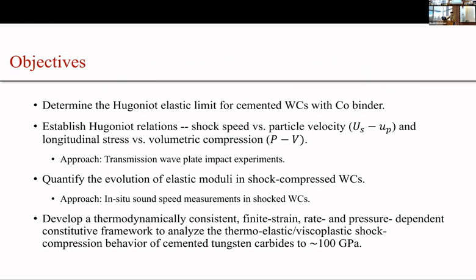The overall objectives of our research are to better understand the structure of shock waves in the cemented tungsten carbide and their associated thermodynamic equilibrium states when it's under shock wave loading. So we're going to determine the Hugoniot elastic limit for tungsten carbide with cobalt binder and establish the Hugoniot relationships in the shock speed versus particle velocity, and also in the longitudinal stress versus volumetric compression plane.